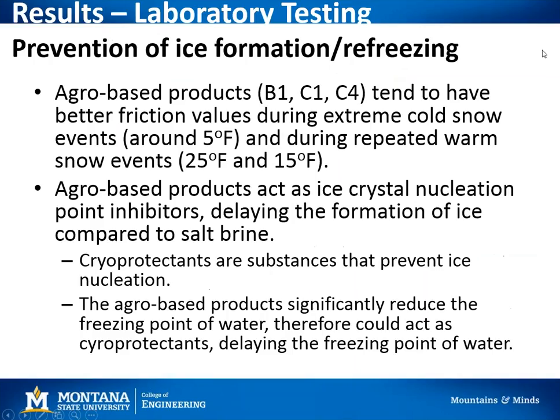So to summarize this data, the agro-based products tend to have better friction values during the extremely cold snow events and during the repeated warm snow events. And the agro-based products act as ice crystal nucleation point inhibitors, delaying the formation of ice compared to salt brine. Now, these are the cryoprotectants I was talking about earlier, which are substances that prevent ice nucleation from occurring. And the agro-based products significantly reduce the freezing point of water, therefore could act as these cryoprotectants, delaying the freezing point of water while not necessarily having a higher ice melting capacity.